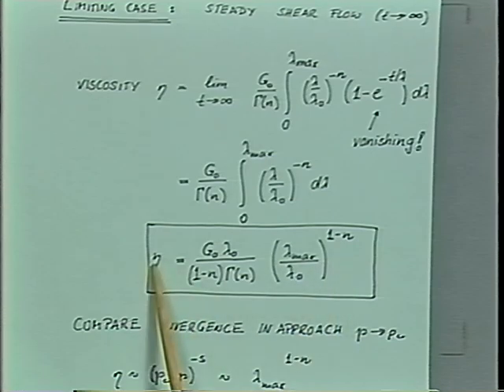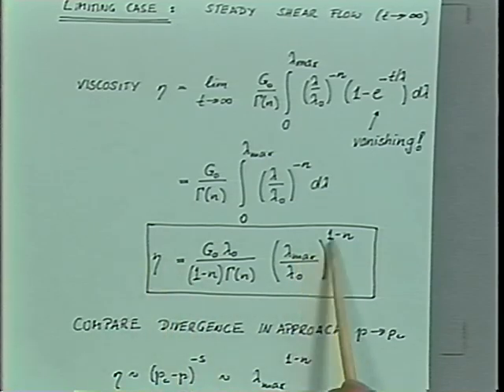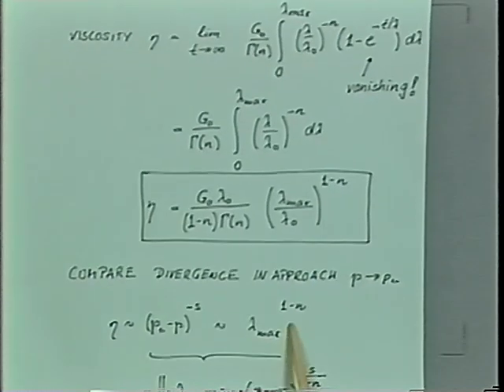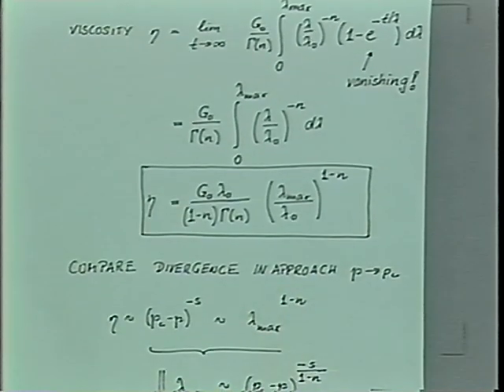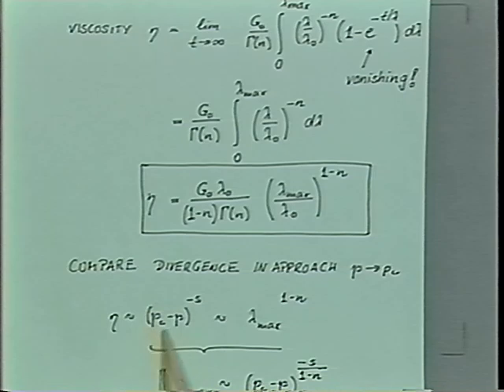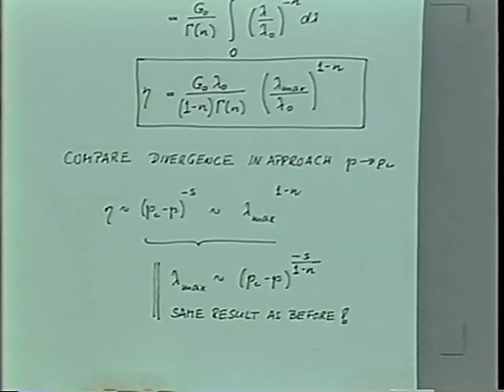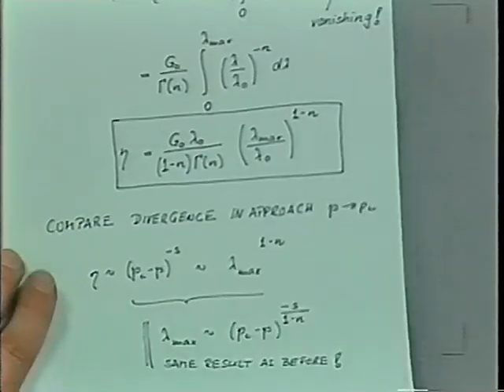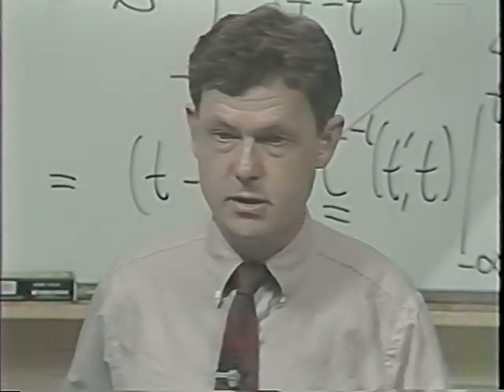And we could use the relation above and say eta is proportional to lambda max to the 1 minus n. Therefore, we could say lambda max goes with the distance from the gel point with minus s over 1 minus n. And this exponent is the same exponent which we already derived from experimental observations two lectures ago. So no difference in the result. It's consistent with the other observations.